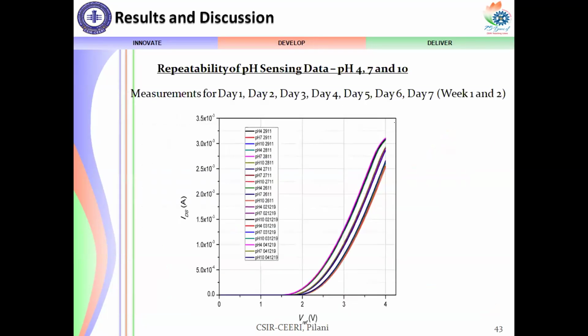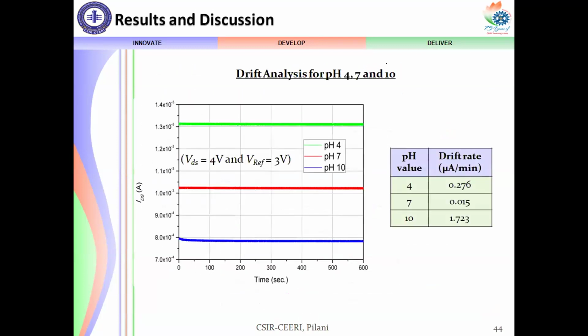Since this material is very stable, we have tested it for many days for its stability at different pH levels, and we got repeatable results. So this is the drift analysis of titanium nitride based EGFET for pH 4, 7, and 10, and the drift was quite within limit, which can be catered for by a suitable electronic circuit.